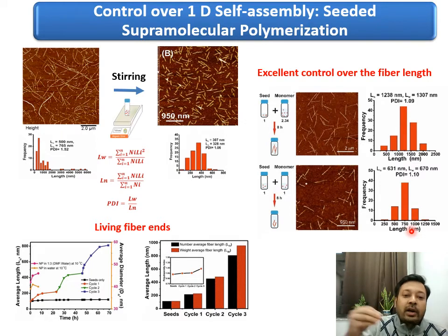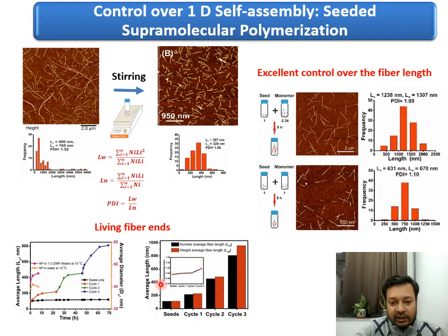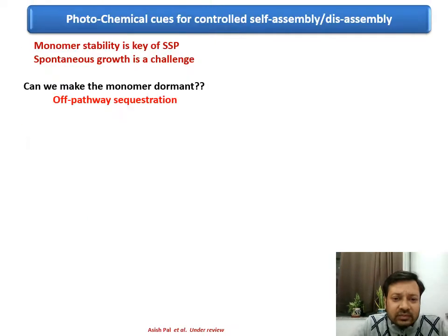You can keep on adding more and more monomer, and it keeps growing. That is very important, because if we can somehow cross-link this material, you can generate very uniform functional control of such hierarchical material. Now, whatever we showed so far is rather on-pathway control over the nanoparticle. However, many a time that is not really that elegant.